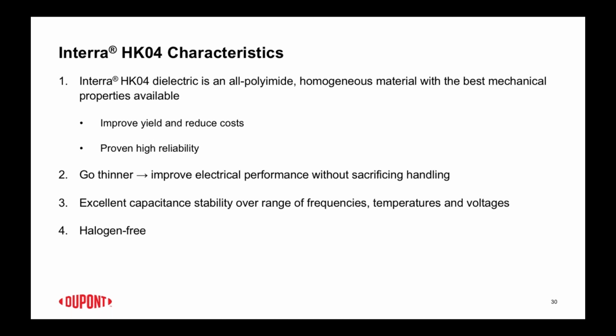Also, you can go thinner without sacrificing electrical performance from a breakdown voltage. Again, because it's a continuous film, you don't have to worry about the things that could happen with fiberglass reinforced materials that may have voids or foreign material, other things that can cause problems. And again, it has excellent capacitance stability over a very large range of frequencies, temperatures, and voltages.